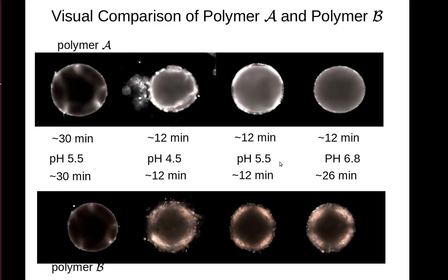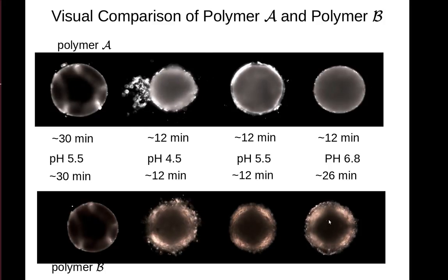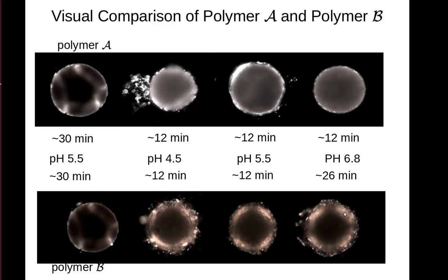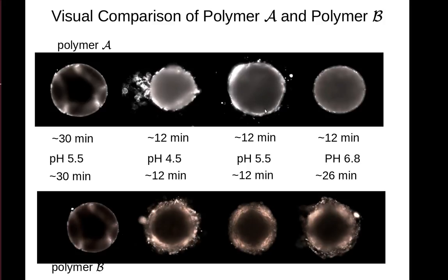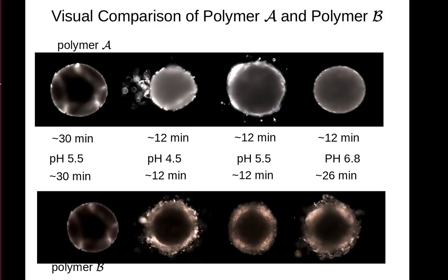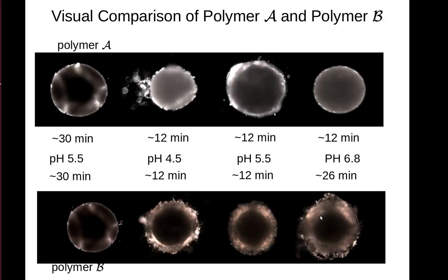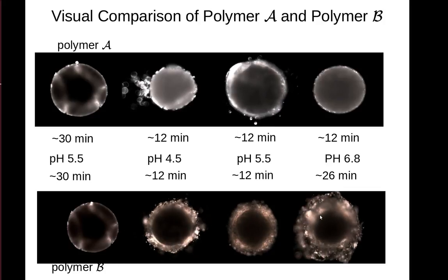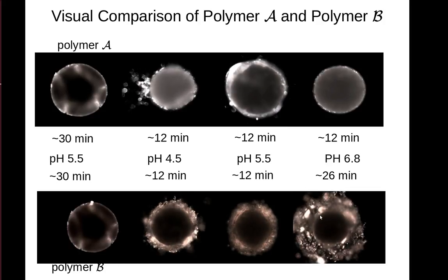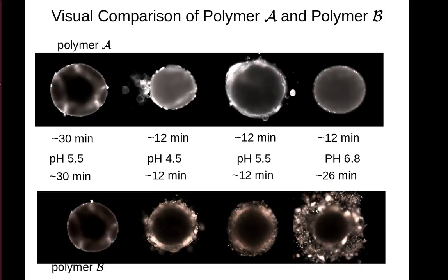So again, comparing the 5.5 of Polymer A to the 6.8 of Polymer B, we see that Polymer A swells and then dissolves. For Polymer B, it swells considerably more, and because of its insoluble nature, we don't really see the polymer dissipate as we do with Polymer A.